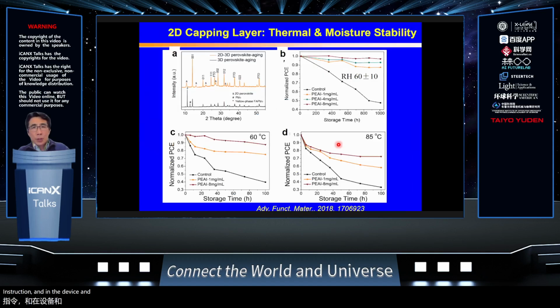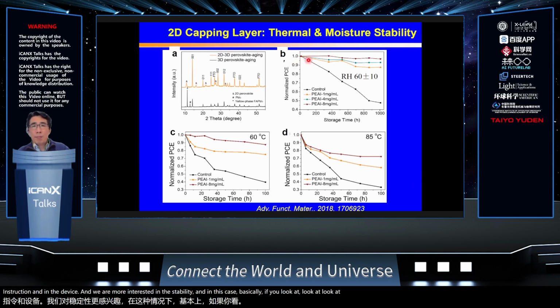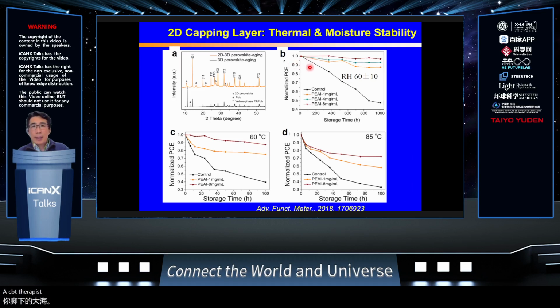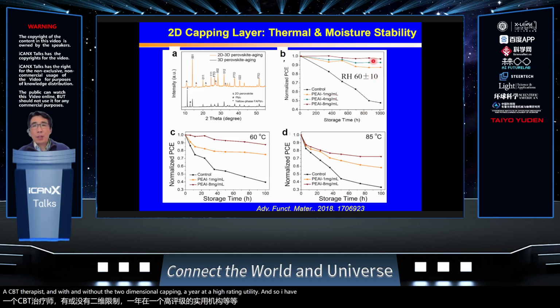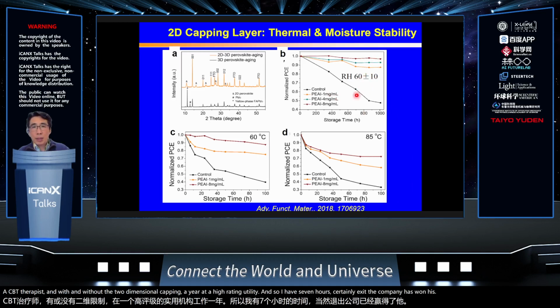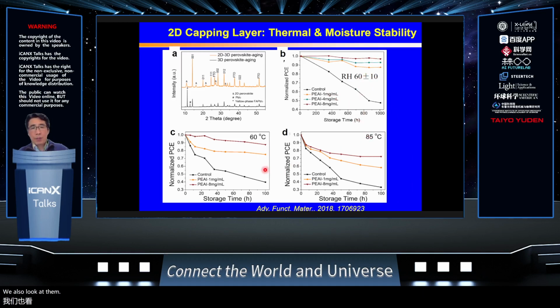And we are more interested in the stability. In this case, if you look at the stability test with and without the two-dimensional capping layer at a high relative humidity, after 1,000 hours the capping layer one is certainly much better. We also looked at different temperatures, and those all showed relatively promising results.